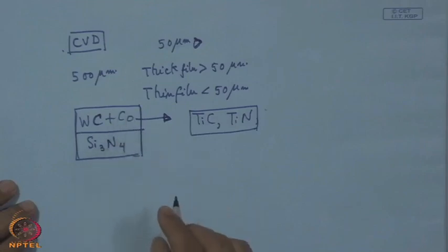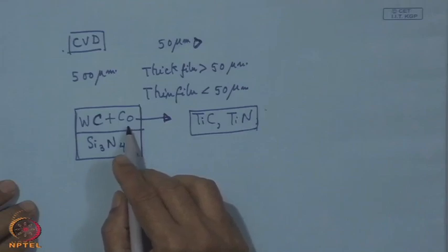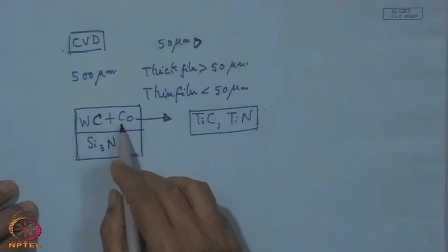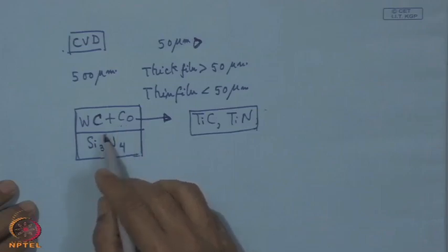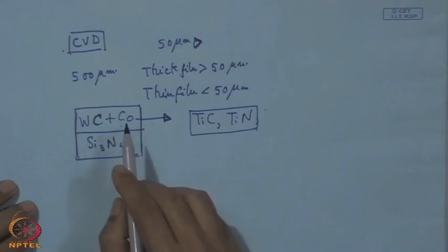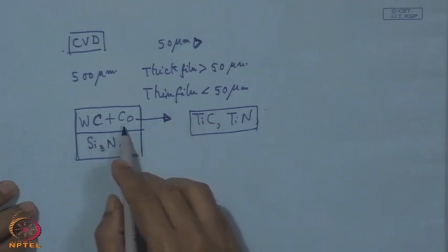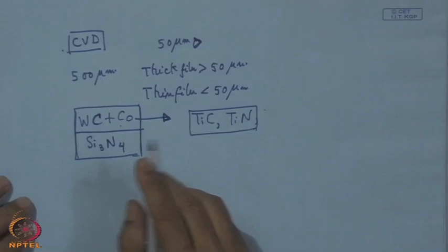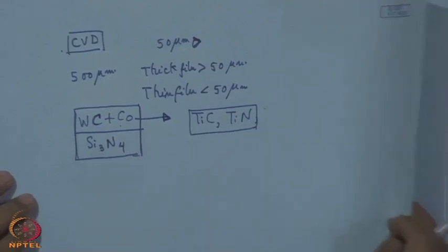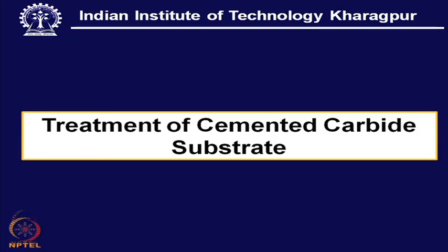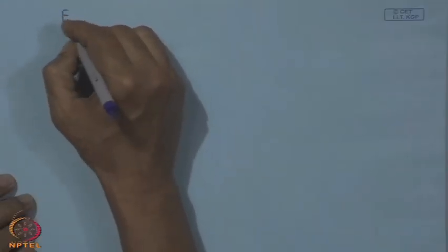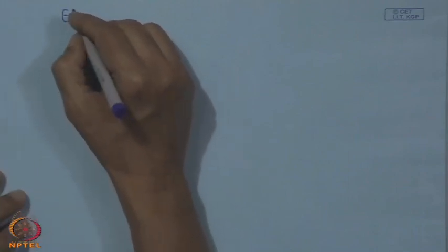Now, when we have cobalt, then the diamond which is deposited on the surface cannot be a stable diamond, and this cobalt tries to make this conversion of diamond to graphite, or nucleation and synthesis, further growth of diamond becomes extremely difficult on cobalt surface. So, here the whole idea is to remove this cobalt. So, treatment of cemented carbide substrate. Here one way of doing the thing is etching of cobalt.